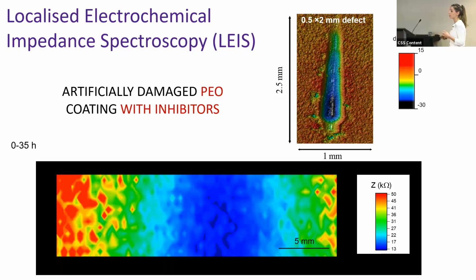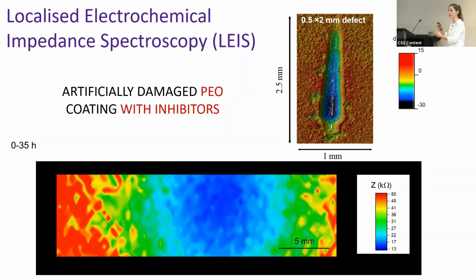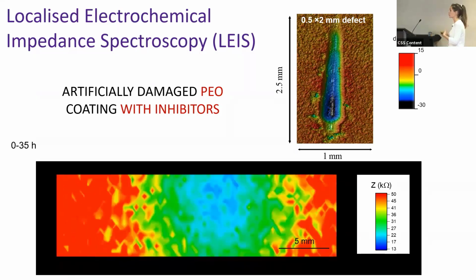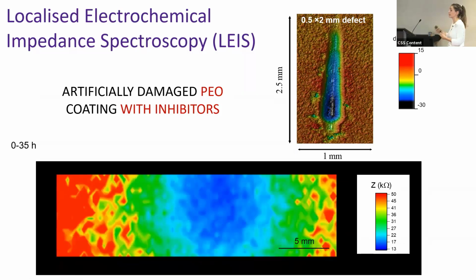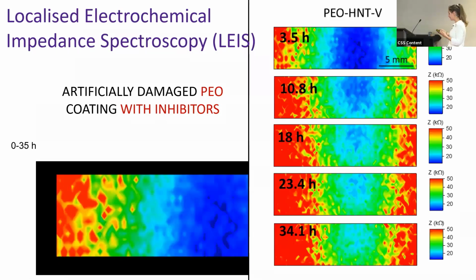So at this stage, probably all the corrosion inhibitors were still encapsulated into the nanocontainers. But as time progressed, the magnesium substrate started corroding, and this triggered an increase of pH as a consequence of the cathodic reaction that led to the release of the corrosion inhibitors. We can see that the corrosion inhibitors acted at the weakest points of the scratch, partially restoring the protective properties.